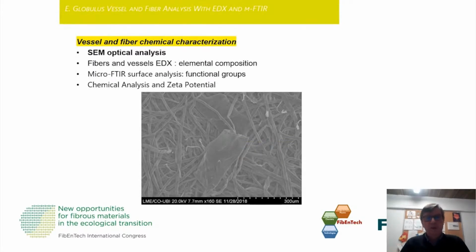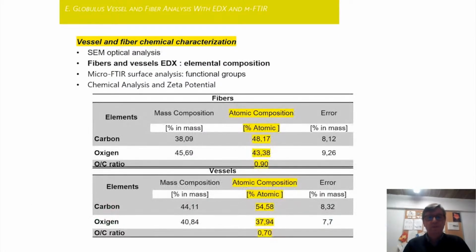We did some optical analysis. We have here a picture. The EDX elemental composition was also done, and we obtained different O/C ratios for fibers and vessels, being the O/C ratio on fibers higher, 0.9 against 0.7 in vessels.